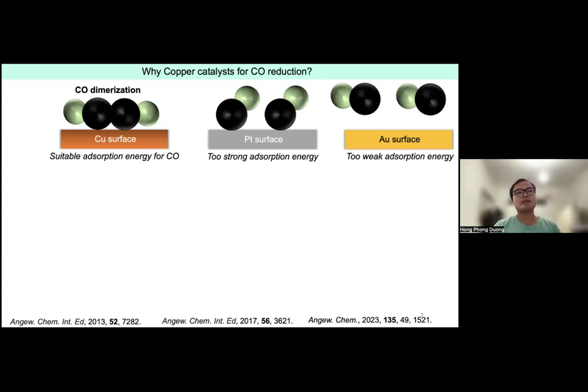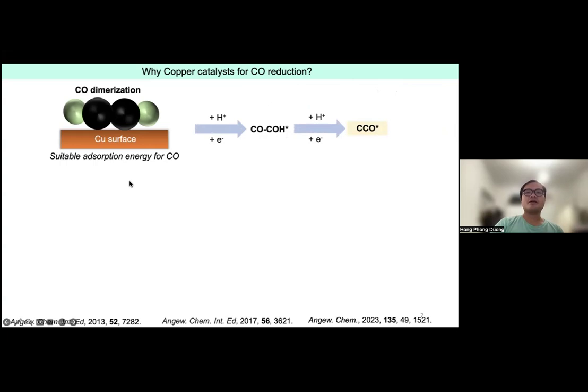And if you check the literature in this field, you will see that mostly people work with silver catalyst for CO. Also, some other metals I can mention are bismuth and tin, which are very good to make formic acid from CO2 reduction. But I will not mention them here. Okay, back to the main thing, the copper. This is good.